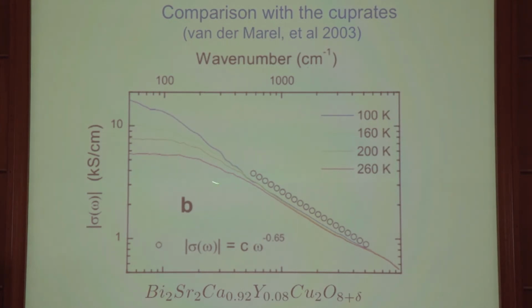And what he finds is very similar to what we see. There's a Drude behavior at low frequency, and a power law at intermediate frequencies. This is a log-log plot. You ask what is the power he sees, and indeed, it's essentially omega to the minus 2/3. This is viewed as a big mystery in the condensed matter community. Nobody really understands why this is coming out of this material, and what we find is that it actually is predicted by general relativity. I can't really tell you why this is working. I mean, this seems miraculous, but it's what we get.